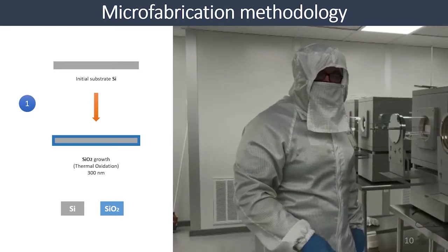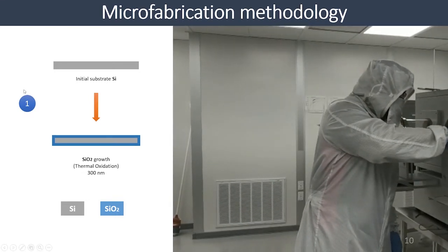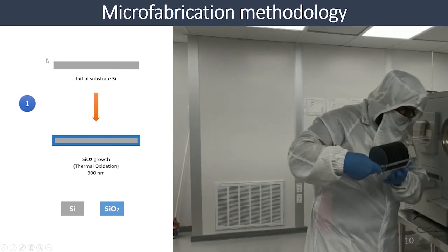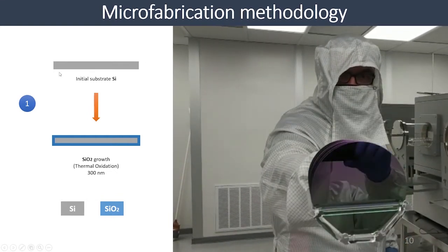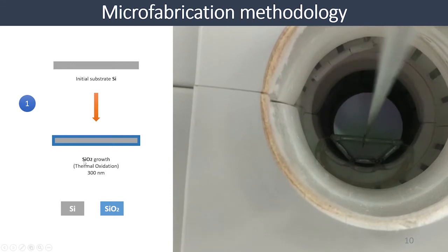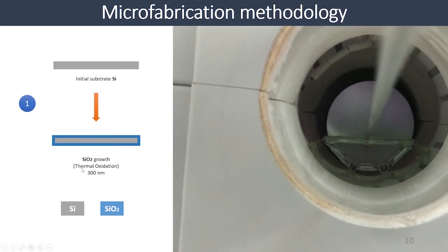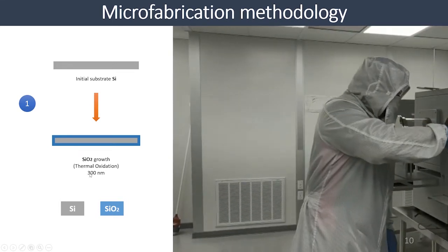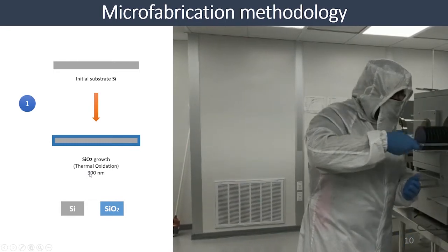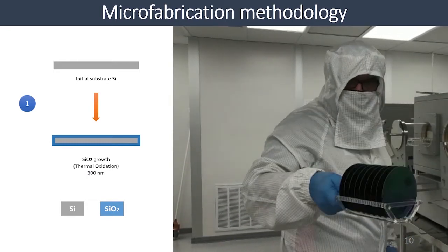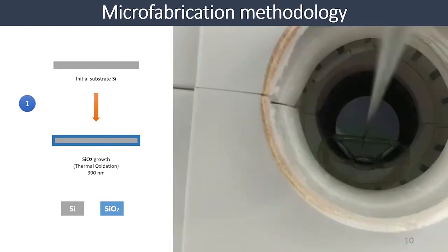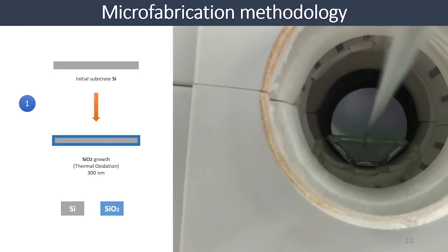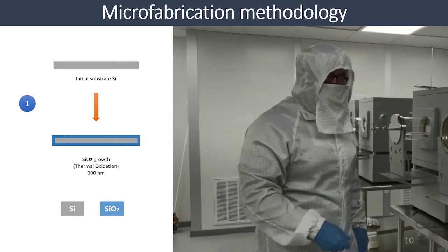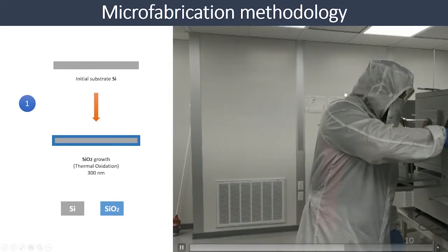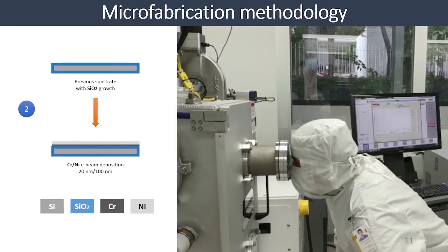On the left side, we can see the transversal view of the process. In step number 1, we start with a silicon substrate. Then we grow silicon oxide by thermal oxidation. We grow 300 nanometers, and this is for two important reasons. One is to isolate the initial substrate from the sensor, and the second is to have a biocompatible contact area. The next step is the thin film deposition.